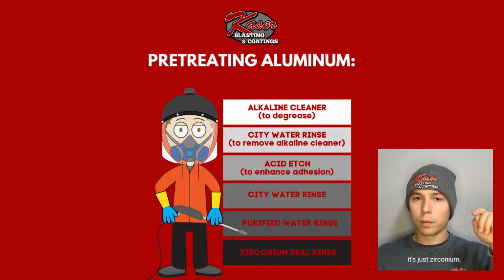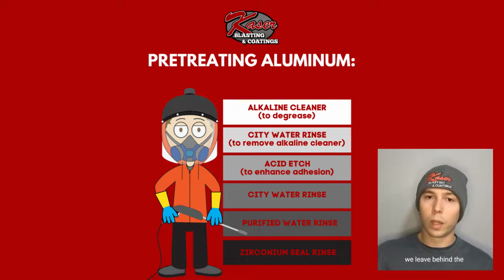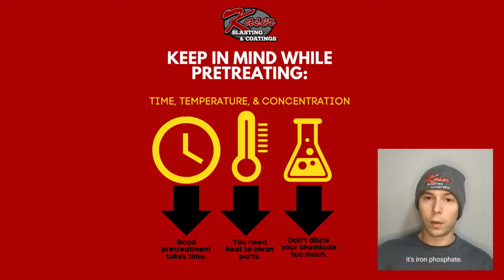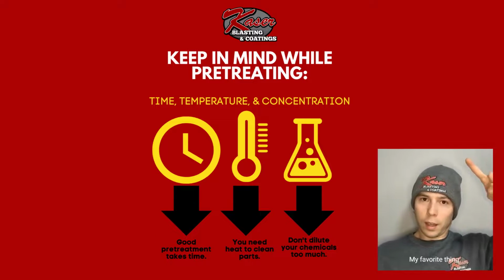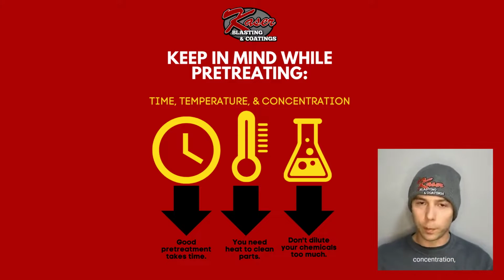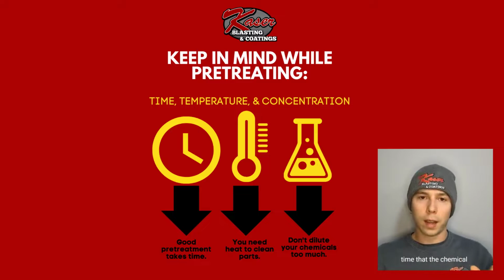It's just zirconium, whereas on steel, when we leave behind a conversion coating, it's iron phosphate. My favorite thing ever, pre-treatment: time, temperature, concentration. Extremely important. If you remember those three things, time, temperature, and concentration, you're going to do good pre-treatment. What do we mean by time? It's the time spent on the part, the contact time that the chemical has on the part.